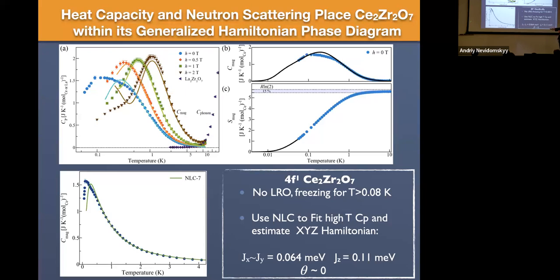The best fit green line is shown here. It doesn't agree at the lowest temperatures, probably for a couple of different reasons, but it does provide a very good description in the region where it's supposed to. I'm not going to show you all the analysis that we did, but we did similar modeling of magnetic susceptibility data and diffuse neutron scattering data. The bottom line is that for this system, we've got no evidence of long-range order, no freezing above about 80 millikelvin, and we can back out estimates for the terms in the microscopic Hamiltonian.